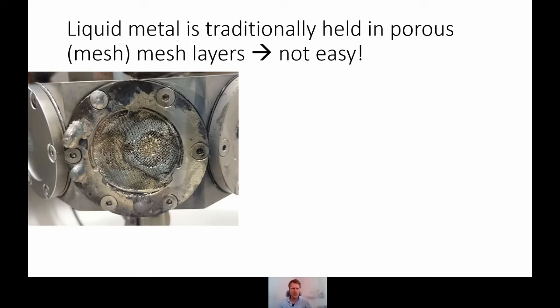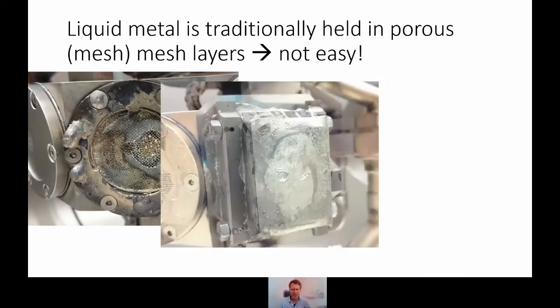One typical way to make these porous structures is to use meshes, so basically layers of woven metal wire. But this is not straightforward. Here you see a sample that we exposed in Magnum at the beginning of my PhD. After a single plasma exposure, we melted through all these mesh layers, and it's a complete wreck, so to say. Then I made another target, and this one has a single mesh layer on the top. But in the middle of that, you can already see there is a hole. Behind that was a reservoir and some other things. But the mesh layer is damaged, and that is not ideal.